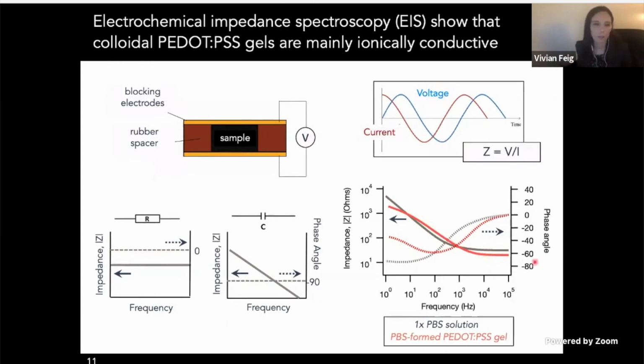So for both cases in this high frequency range, what we see is that the phase shift is around 0 with a frequency independent impedance. And that's indicative of there being these ionic charge carriers within the material that can enable the circuit to look like a resistor at these higher frequencies. But once you get to lower and lower frequencies, those ionic carriers start to saturate at the electrodes, and it begins to resemble a capacitor, which is why you have this really dramatic impedance increase.